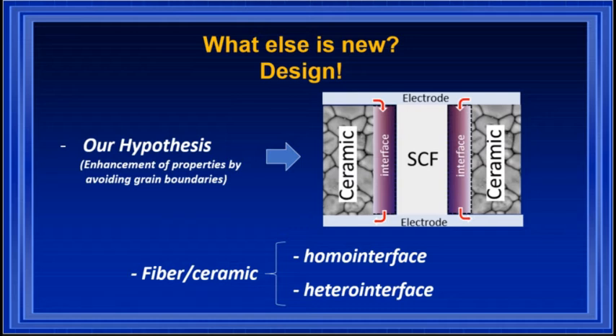We think that we can improve the design of the electrolyte. If we think of an electrolyte as a material that sits between two electrodes, and we are searching for a better ionic conductivity in this solid-state electrolyte, then this is our hypothesis: if we combine ceramics with single crystal fibers that interconnect the two electrodes, it will create an interface that can interconnect the two electrodes without any grain boundary. That's our hypothesis, to try to improve or enhance the ionic conductivity in solid-state electrolytes.